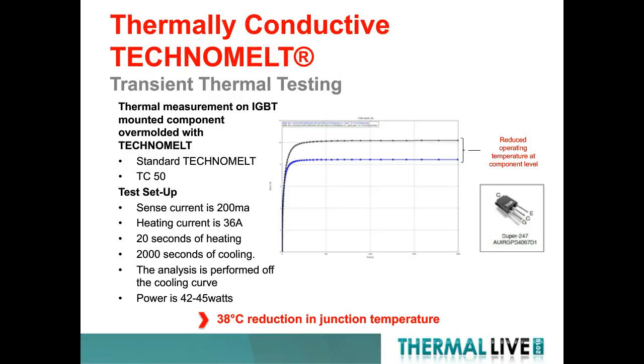Those pins were then placed into a jig that was used to power up the device itself, and we were able to monitor the heat curve, or the cooling curve in this case, for that particular component. So the test setup used a sense current of 200 milliamps, heating current of 36 amps, 20 seconds of heating, so we turned the heat on for 20 seconds, and then monitored for 2,000 seconds on the cooling curve. The analysis, or comparison, is performed off the cooling curve when the power reached 42 to 45 watts. So pretty high power for these devices themselves.